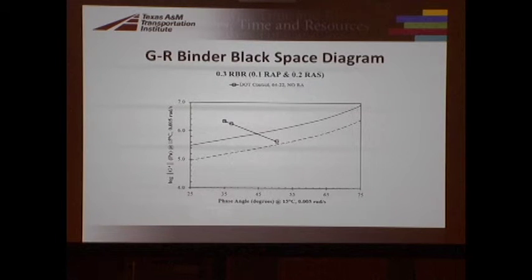So this is that DOT control binder, and this is the black space parameter. This is log of G* at 15C and 0.005 radians per second versus phase angle at 15C and 0.005 radians per second. So this is showing stiffening or softening, and this is showing flexibility or embrittlement. Okay, so it's capturing both rheological parameters on a single plot.